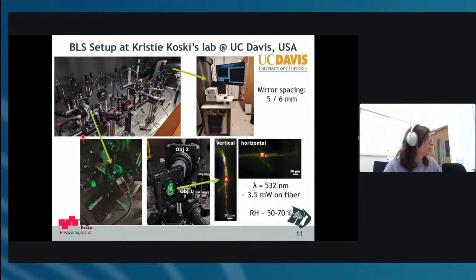Yeah, and we mounted the samples here in the middle. You see here, we're always measuring with green light at 532 nanometers. And what you see here, there are two objectives, one for the incoming and one for the outcoming light. Sometimes you can also do the measurements where both the incoming and the outcoming light go through the same objective. And basically what I did is I just mounted the fibers in.